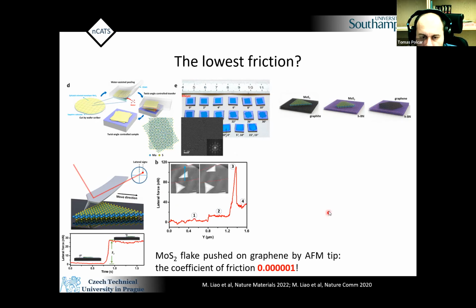And of course, we coupled it with simulation, and there were 2 reasons why we did the simulation. One of the reasons is that we need some information about adhesion, which experimentally is very difficult to get. So we basically calculate the adhesion between the flake and substrate, and this we use to calculate the friction here. So this is how to get the lowest friction.